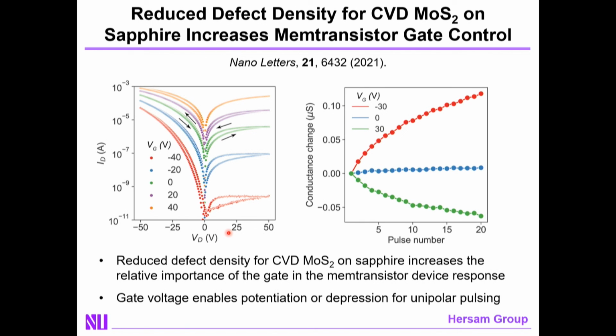Or equivalently, what you're doing is increasing the influence of the gate voltage in this device. So the transistor response or the gate control will be enhanced if you reduce the defect density in your polycrystalline MoS2. This is indeed the case. In fact, you get so much tunability over the synaptic response that you can tune with single input bias polarity from a potentiation or increasing in conductance behavior to a depression or reduction in conductance behavior for the same voltage polarity. This is exactly what happens in neuroscience.